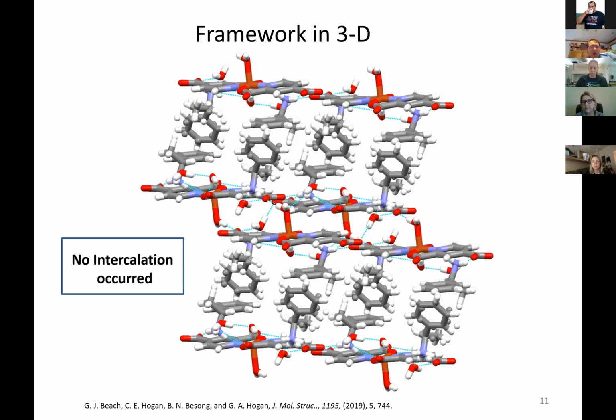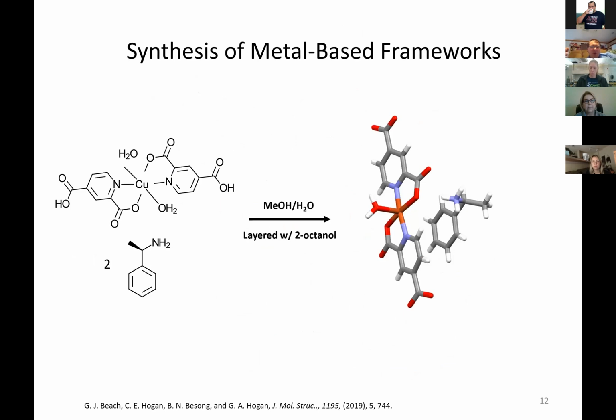The reason is we chose something very large when we tried the initial synthesis of our crystal. So we decided to scale things back a little bit, and we ran the exact same crystallization process. This time we chose to layer with a variety of what are called alkyl alcohols. We used 2-octanol, a carbon chain 8 carbons long with an alcohol OH group at the 2 position.